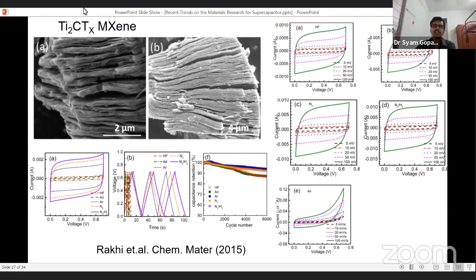See here, it's like titanium carbide MXene. Here we can observe it's like a pack of cards, almost similar to graphene's stacking. So if metals can intercalate into the surface area, then the electrolyte ions can explore the higher surface area of the material, thereby increasing the capacitance.